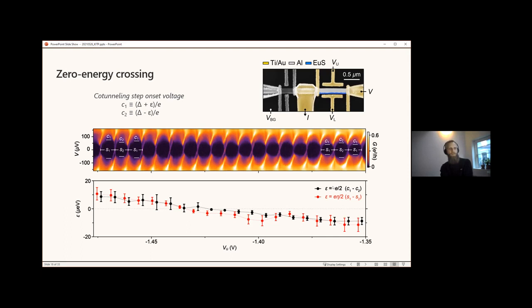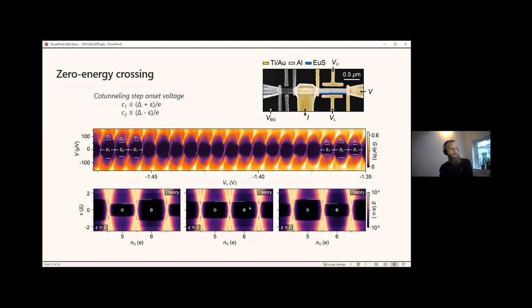Finally, we can compare those data with the theory for a subgap state energy larger than zero, and we find that the odd diamond is smaller than the even diamond. If the subgap state energy is brought to zero, we find that both diamonds are of the same size and the Coulomb features align with each other.